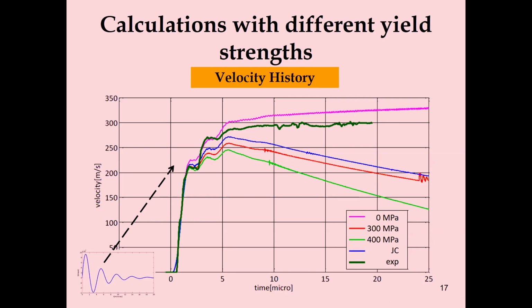So looking at what I just said, if we're looking at this almost horizontal line, you would say, okay, there's no strength in this kind of test we examined, but that's not right. And this is the part I'm not getting into all the details of, but between 5 and 6 microseconds since the beginning of the expansion, we're getting failure of the cylinder. So in fact, this horizontal line is just looking at a fragment which detached, and we have no hoop stresses, so it looks like we're not getting any strength at all.